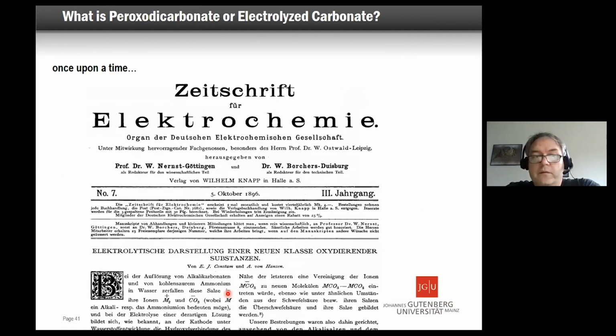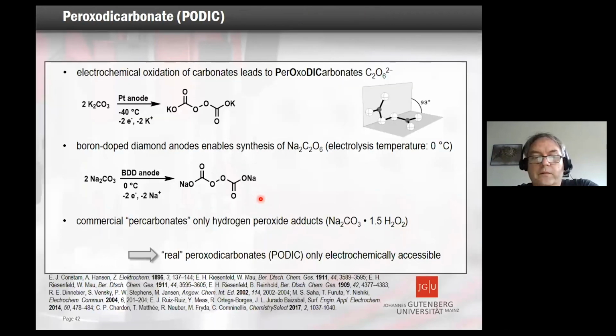Well, this is very old chemistry. It was done many, many years ago, more than 120 years ago when they made it. And what is the reason behind it? What did they do? They used carbonates. If you oxidize carbonates in a relatively brutal way, the oxygen-oxygen bond is formed. This allows you to make this compound. You see, this is very specific; you cannot use that for an efficient synthesis. The structure was verified many years ago. And with the use of boron-doped diamond, you're able to make this kind of compound a little bit more easily.